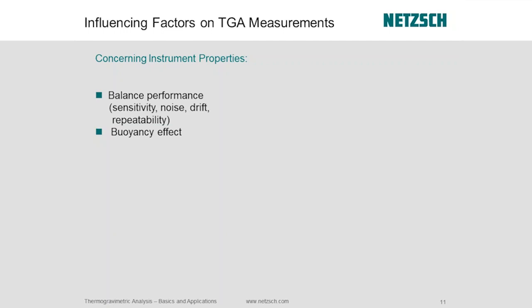The extent of the buoyancy effect depends on the design of the TGA. We do a lot at NETZSCH to minimize the buoyancy effect, but then it's very, very easy to correct as well just by running a blank run. You take your empty crucible and run a blank run over your temperature conditions and with your gas settings, and that is stored digitally and then matched up against your sample curve and subtracted out. So that's the normal way to deal with the buoyancy effect, no matter what type of TGA that you have. We recommend that. But we also have in some of our newer instrumentation software techniques that accommodate the buoyancy effect digitally, built into the software. So you don't have to always run a blank run anymore if you've got some of the newer design instruments.